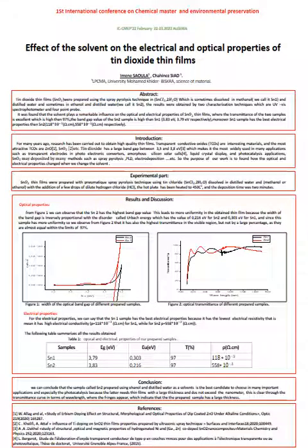Moreover, SN2 has the highest transmittance in the visible range, with wavelengths between 400 and 800 nanometers, as shown in figure 2. But in general, the transmittance of the two prepared samples, SN1 and SN2, are almost equal, within the limit of 97%.